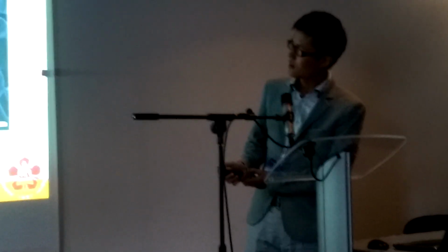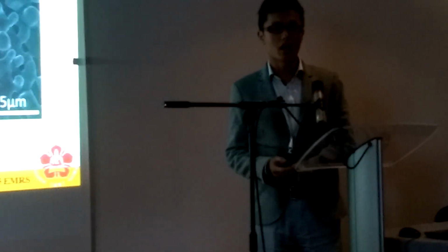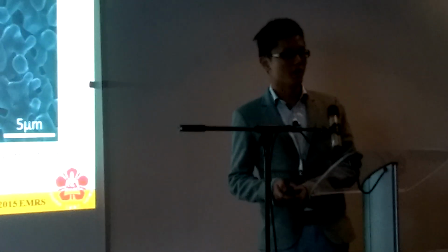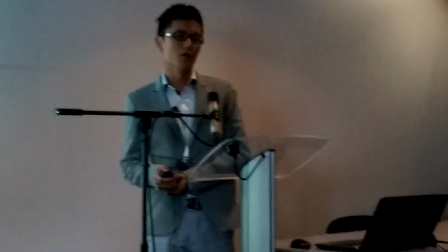When we raised the temperature to 1000 degrees Celsius, figure 2D, we found a thin film on the substrates again, but with coarse grains. At high temperature, it was easy for our precursor iron chloride to transform into vapor phase and be transported to the substrates, which quickly increased the reaction concentration in the closed tube. So the reaction rate in the furnace was really fast, which changed the morphology of our products from nanowires to thin film.